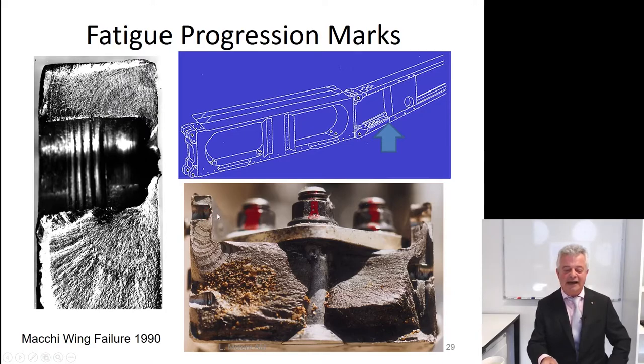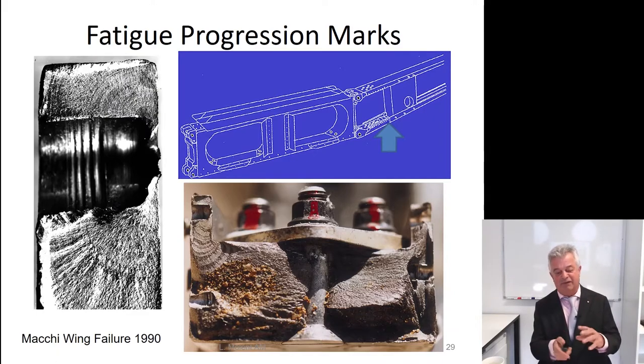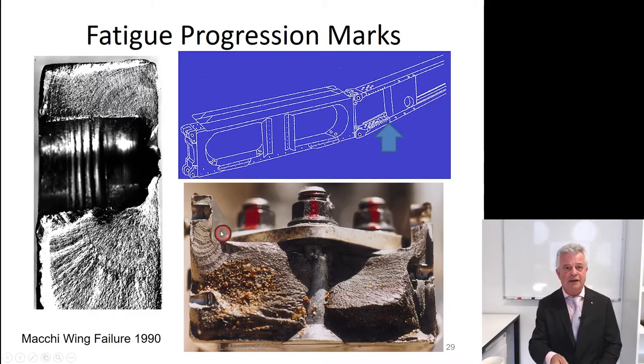Long story short, the artisan who created this hole pierced the back face, leaving a very sharp flute, very high loads. Fatigue says, thank you, I want that. It nucleated and grew quite rapidly to failure in something of the order of maybe 50% of what the design life of that spar was. Did I mention two people dead due to what we call, let's call it inadvertent poor quality, okay? Aircraft are very sensitive to inadvertent poor quality.